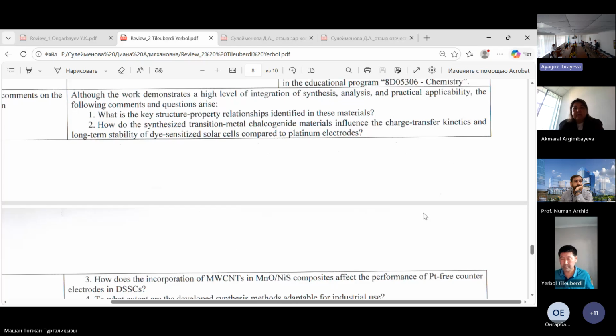Thank you for your questions, Professor Erbol. Regarding question number 1, the key structure-property relationships identified in these materials are associated with composition tuning, nanoscale morphology, and interface engineering. The incorporation of transition metal and conductive components improves electrical conductivity and increases the number of active catalytic sites, while nanowires and porous structure enhance surface area and charge transfer. Additionally, heterointerfaces and defect structures promote fast electron transfer and improve electrocatalytic and photovoltaic performance.